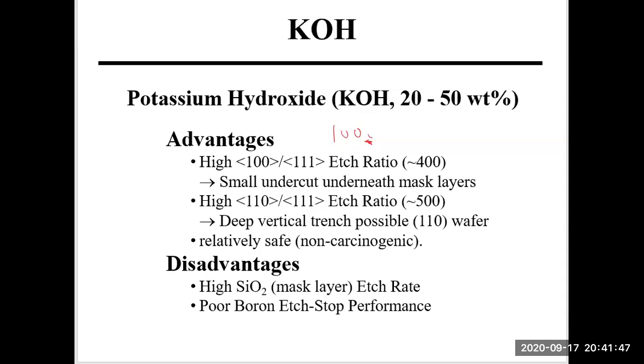So this etch ratio of 400 basically means if the 100 plane is etched by 400 microns, the 111 plane is only etched by 1 micron. So this etchant is very anisotropic. The ratio is 400 to 1. This leads to a very small undercut underneath the mask layer.